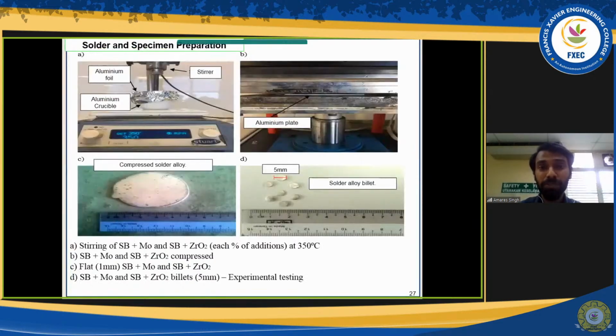Once cooled, we will have the solder alloy. Of course, it is important for me to check if the nanoparticles are there. I can't cover every study, but I did use X-ray diffraction, which showed the presence of zirconia and molybdenum in my solder alloy mixture. So the experiment has passed the first stage of proving that the nanoparticles are in the solder alloy, because if not, there's no point in adding nanoparticles if I can't find them inside. After that, I have to go through a remelting process, just to make sure that the nanoparticles are properly mixed. Then I go through compression to make it smaller in size.